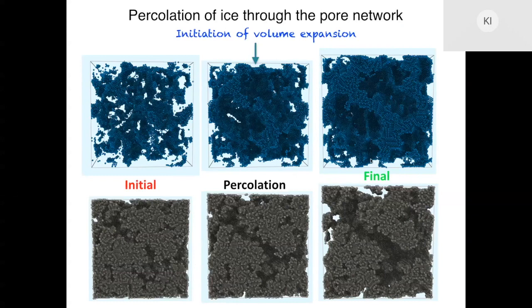So we have clusters of ice inside the pore. Where we start observing the macroscopic volume changes is when we have the percolation. Once the ice is percolating through the network of cement, it has basically a collective effect that is pushing the whole solid of cement, and that's why we're observing a macroscopic volume change. And of course, finally, we have the formation of really large cracks.